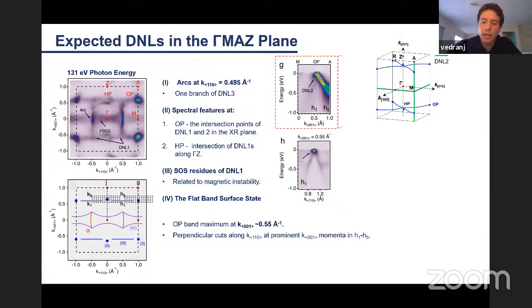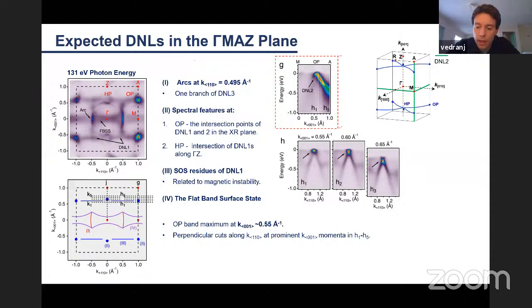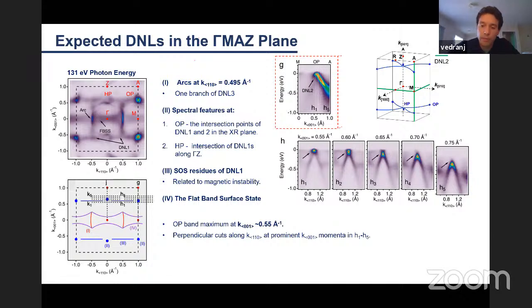So let's take a look at the expanded area of the Dirac nodal line 2 dispersion along the ML line. It essentially highlights the band maximum at the octuple point, as you can see in this middle red circle. And if we take perpendicular ARPES band structure cuts at prominent momenta, shown by these white lines, we plot them in H1 to H5, they reveal for us the appearance and the evolution of the Dirac crossing between the OP and A. And the curvature exemplifies this crossing and shows essentially excellent agreement with the DFT prediction that I've shown you earlier.